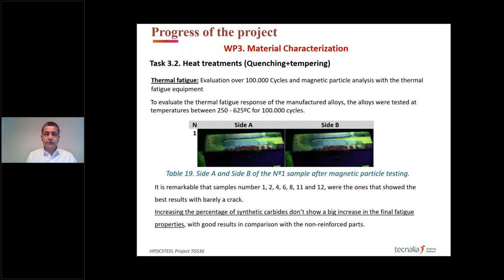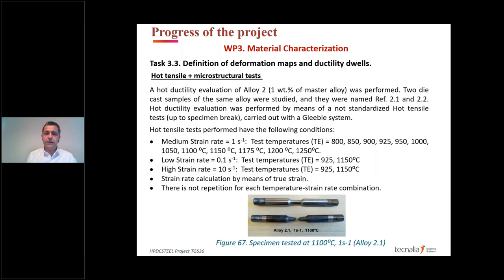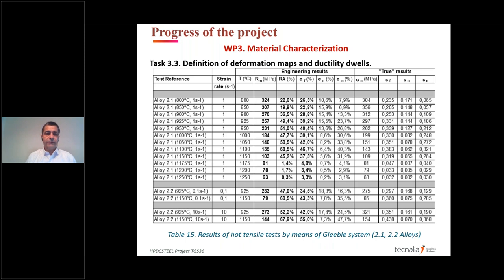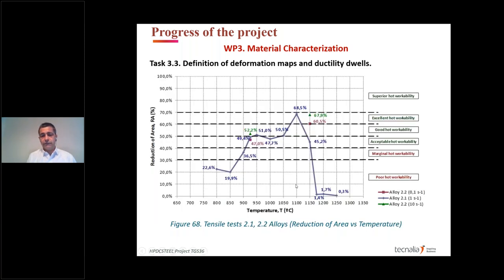So here we have the results. In thermal fatigue, we checked the three materials and observed very small cracks after 100,000 cycles, which was also a good signal. We also made some tests with the Gleeble machine in order to determine the behavior of this material at different strain rates and different temperatures. Here we have all the tests, at different temperatures from 800 degrees to 1250 degrees, at different speeds from 0.1 to 10 per second, and we determined that there is a range of temperatures and a range of reduction where we can work properly with these alloys.